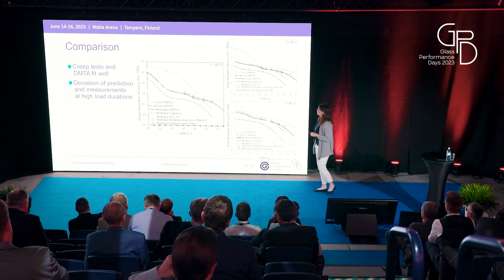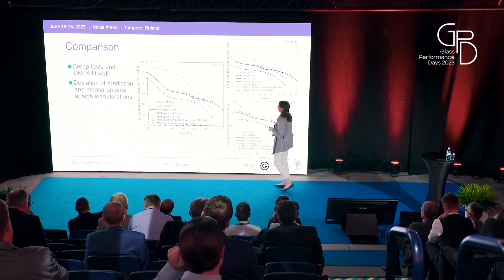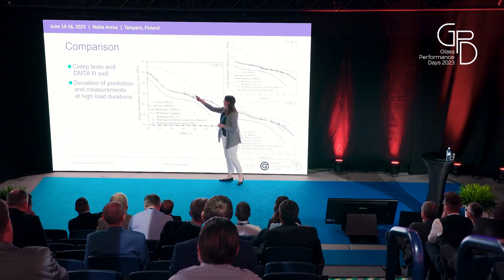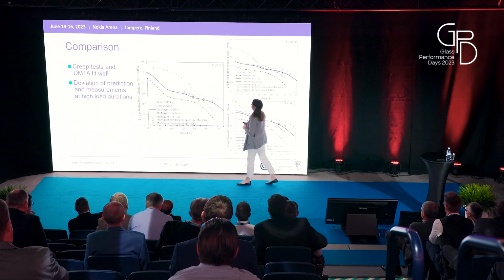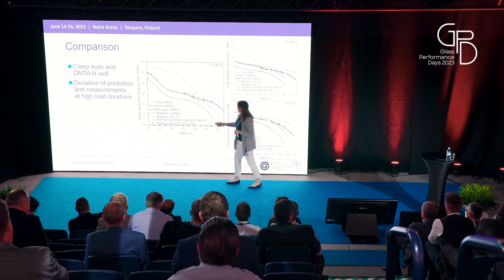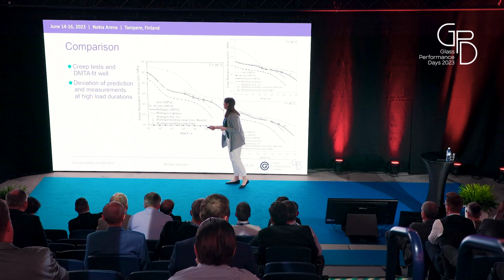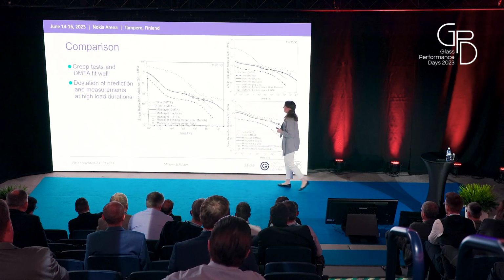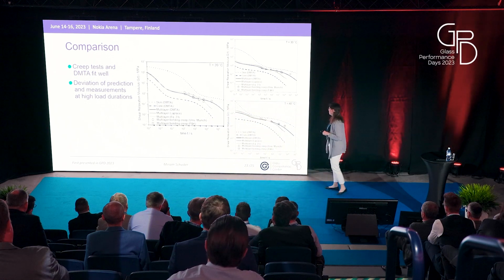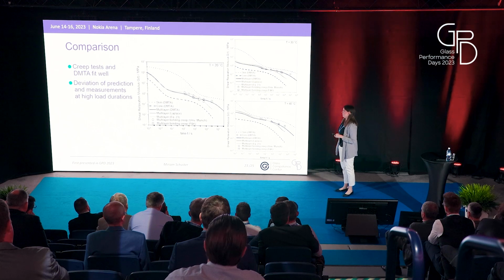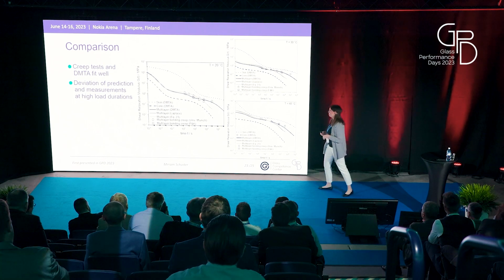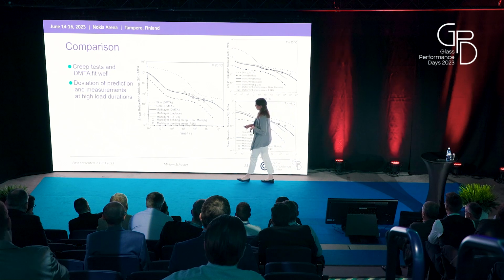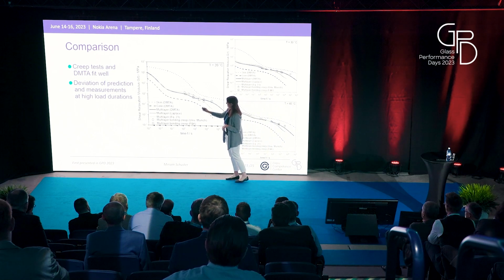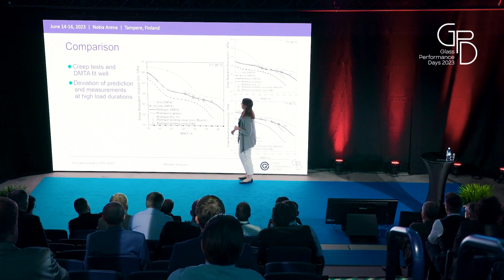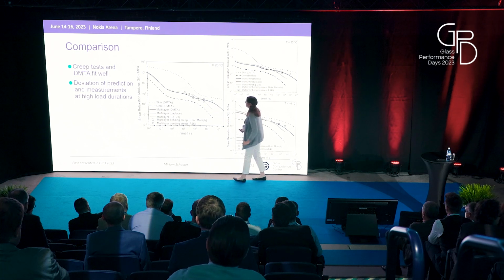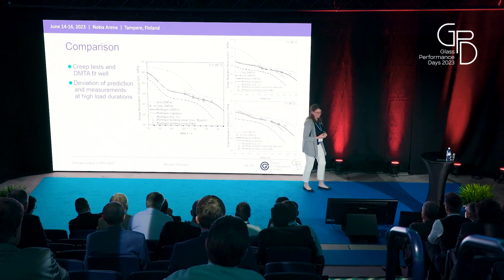However, when looking at our prediction, we see that also the prediction fits quite well to the creep test until we arrive at higher load durations. There we have a deviation, and we still don't really know where this deviation comes from. Mathematically speaking, it comes from the decrease of the stiffness in the core layer, but why we don't observe it in the bending test is not clear yet.